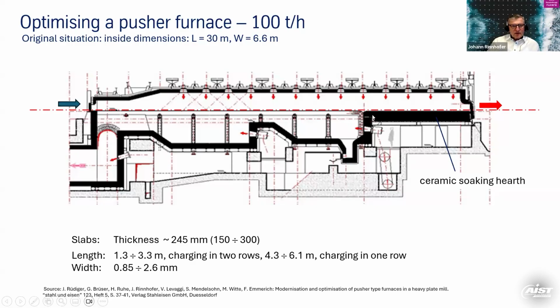And that furnace has a soaking zone like traditionally built as a ceramic soaking hearth, basically. That's the usual way they built the furnace in earlier times. So we have the flue gas going out through the bottom here, which is actually a good solution. We don't want to go up here if possible, so we want to go down in order to drive the flue gas down over the slabs into the flue gas duct. We have a little convection zone here, and then very large burners here on the bottom of the furnace in the heating zones here, and a lot of roof burners here.